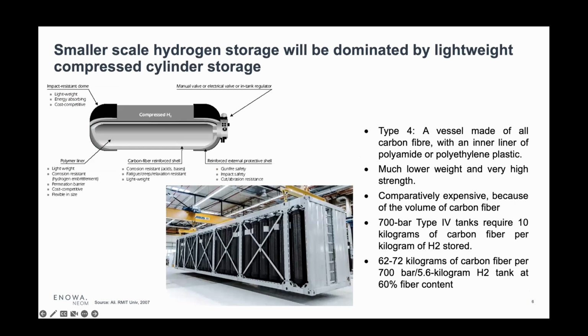At smaller scales, the technology is quite mature already. Essentially, what we have is lightweight compressed cylinder storage. This is today the most effective, cost-effective, and lightest way of transporting hydrogen over short distances. This is what we use in NEOM now for hydrogen storage at small scale. Again, this is in the range of hundreds of kilograms to several tons. Essentially, it's a carbon fiber composite vessel with a polymer liner. The reinforced shell allows for corrosion resistance. It's lightweight, and it can contain the pressure.